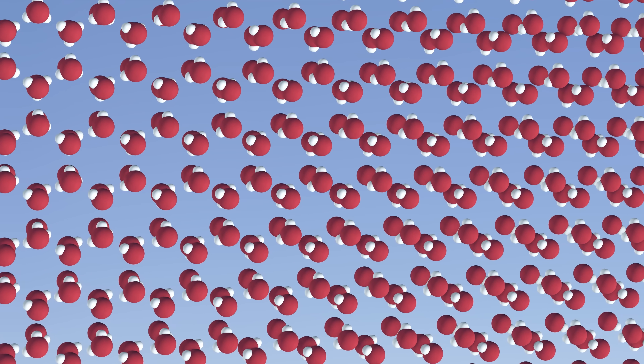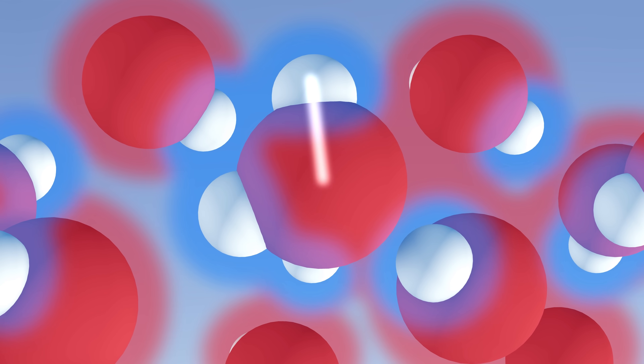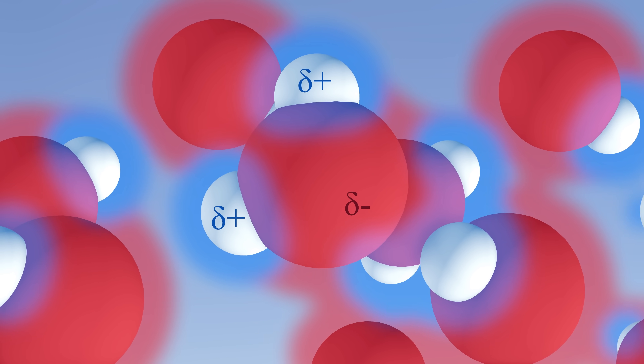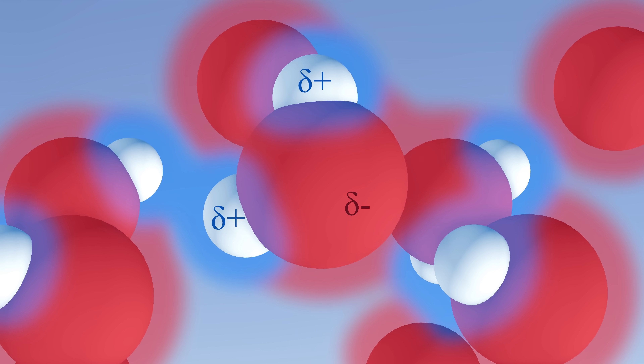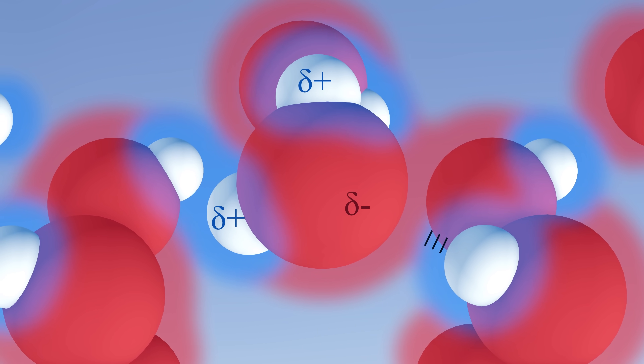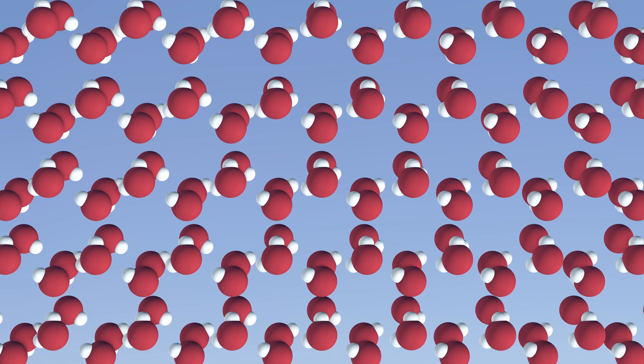This structure results from the peculiarities of water molecules. Oxygen atoms attract electrons more than hydrogen. And since the molecule has a bent shape, it's polar — with oxygen being slightly negative and the hydrogens slightly positive. Since unlike charges attract, a hydrogen from one molecule will sit next to an oxygen from another molecule, forming a so-called hydrogen bond. And this is what creates the hexagonal molecular lattice.